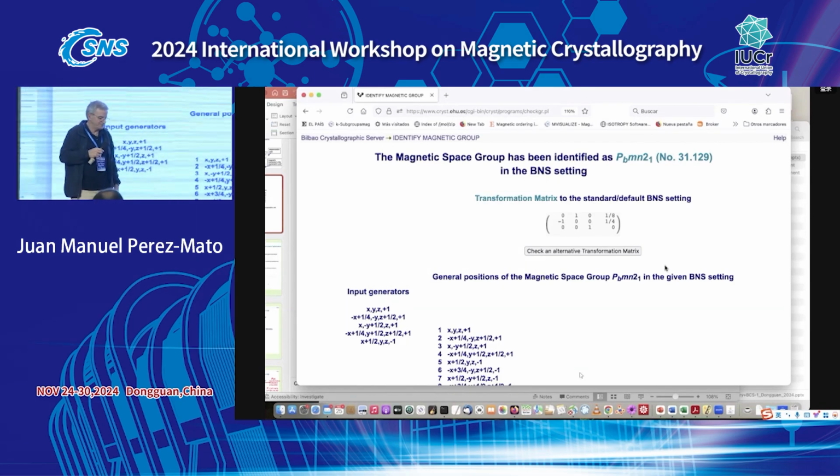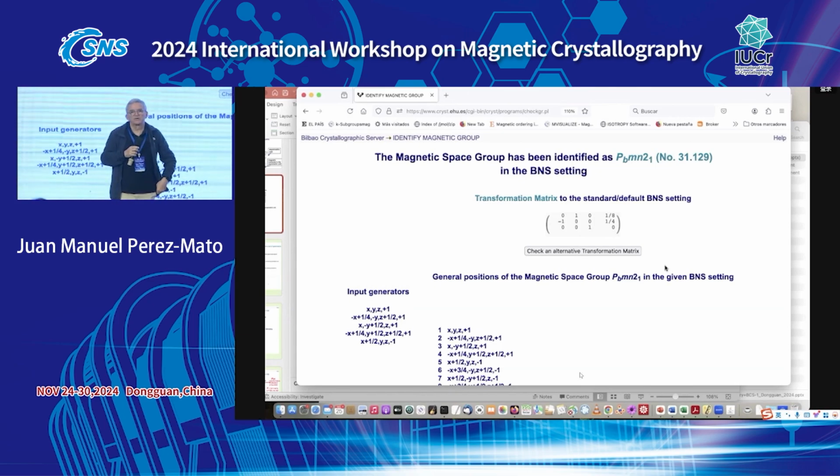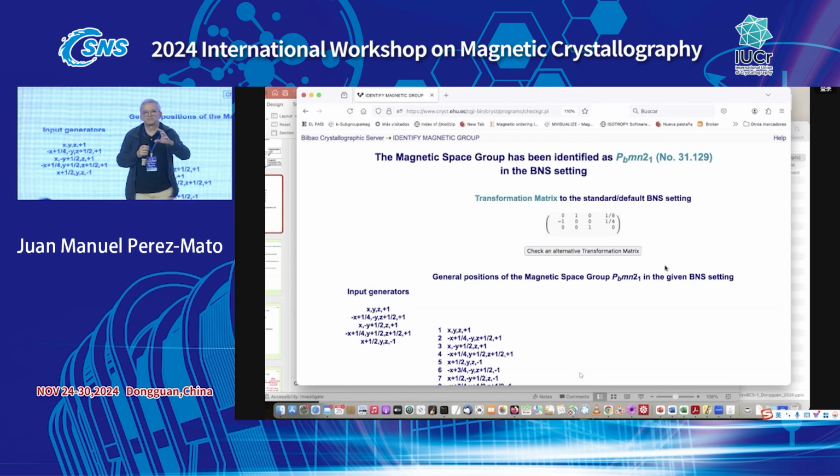In ordinary crystallography, it is not usual to work in non-standard settings. Normally, even if you have a phase transition from, let's say, hexagonal to orthorhombic, and you are in the orthorhombic phase, you go to the orthorhombic unit cell and you describe your orthorhombic phase in the standard setting of this space group. In magnetic structures, it is not. It could be done, but the point is that we have started to use magnetic space groups. Okay, so people are used to work with the image of the paramagnetic structure, and they don't want to go into a description which is not related with these paramagnetic structures in an obvious way.